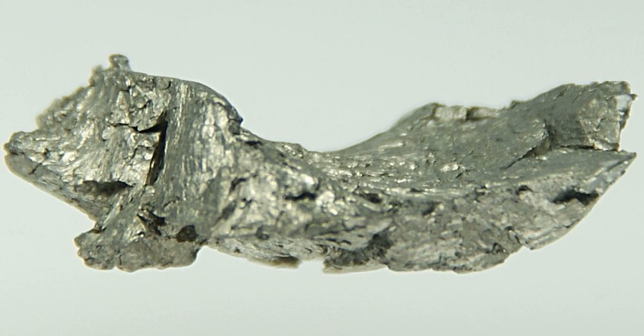Characteristics: physical properties. Gadolinium is a silvery white malleable and ductile rare earth metal. It crystallizes in the hexagonal close-packed alpha form at room temperature, but, when heated to temperatures above 1235 degrees Celsius, it transforms into its beta form, which has a body-centered cubic structure. The isotope gadolinium-157 has the highest thermal neutron capture cross-section among any stable nuclide, about 259,000 barns. Only xenon-135 has a higher capture cross-section, about 2.6 million barns, but this isotope is radioactive.